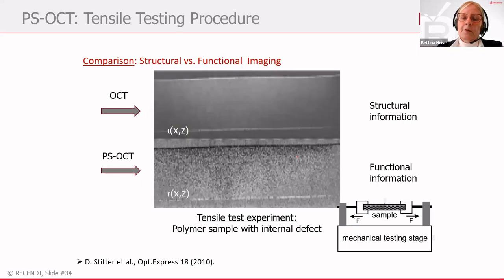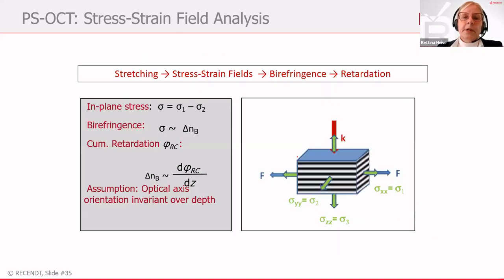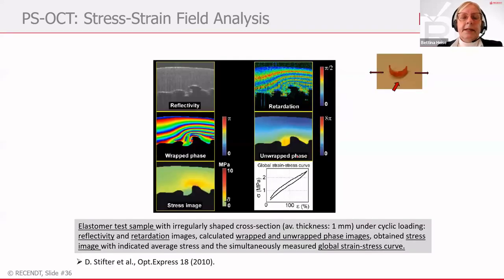In the context of polymers, this is often information about stress and strain states. One can also do some analysis coming from such a polarization-sensitive scan to finally get information about the stress. More or less the density of these fringes can encode the strength of stress in such types of polymer images.